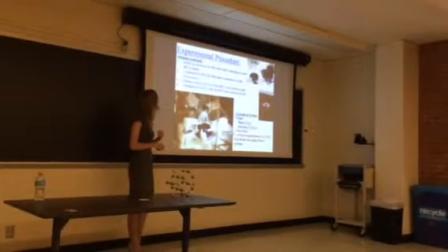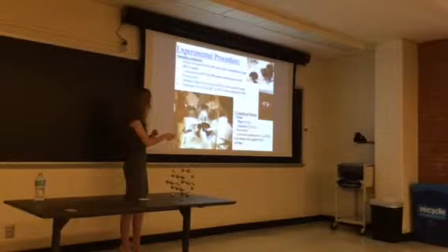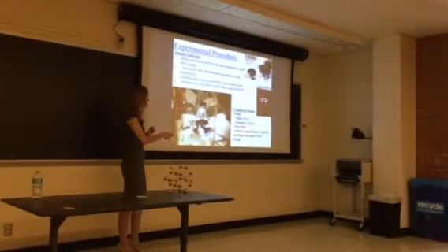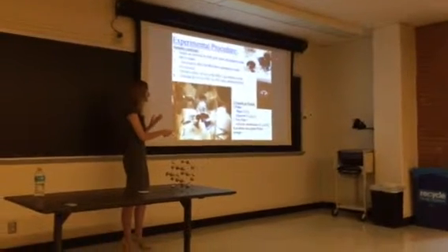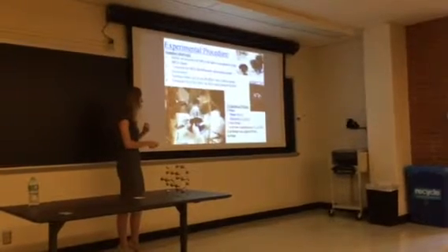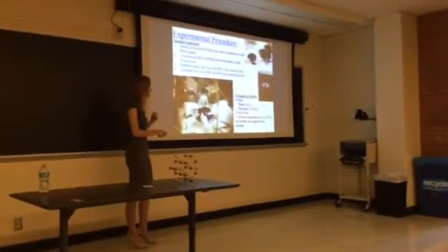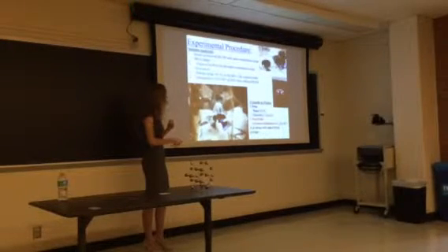Our experimental procedure was relatively simple. We would put water droplets on the wafer and take a picture of them, and then reorient the camera and put glycerin drops and take a picture, and the same with alpha-bromonaphthalene. And then these pictures were uploaded, analyzed, and fit with ellipses, such as this one. And this is the droplet, and this is the reflection of the droplet right here.